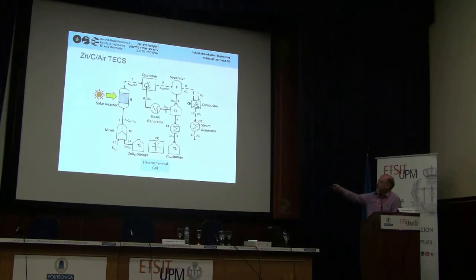Here we have CO and zinc gas. Here we have a quencher to reduce the temperature until the zinc vapor is condensed. And once we have liquid zinc, we can separate more easily from the CO. This has to be very fast, because if we do it slowly, then the contact between the zinc vapor and the CO will cause the reverse reaction to occur, and again we get zinc oxide. This is not good, so this is an interesting challenge, how to make this cooling fast enough.